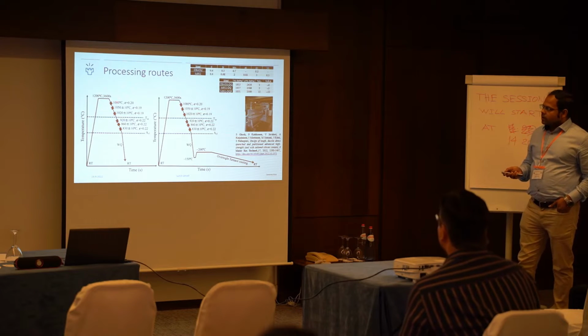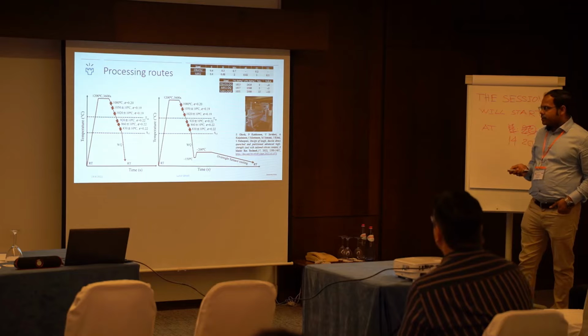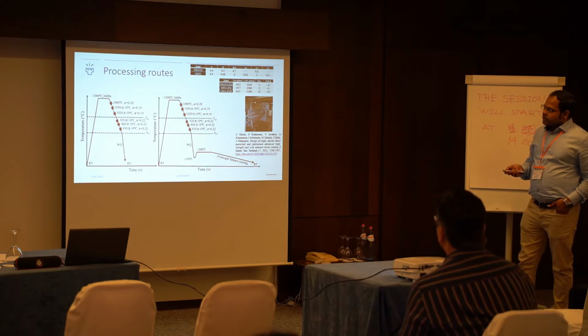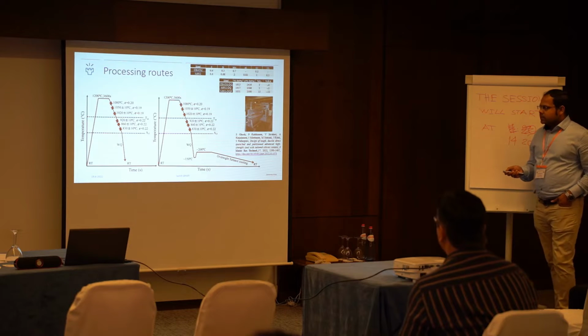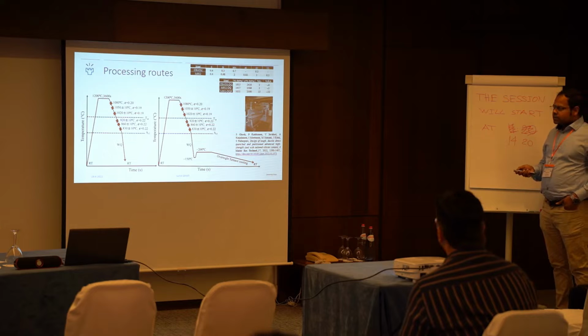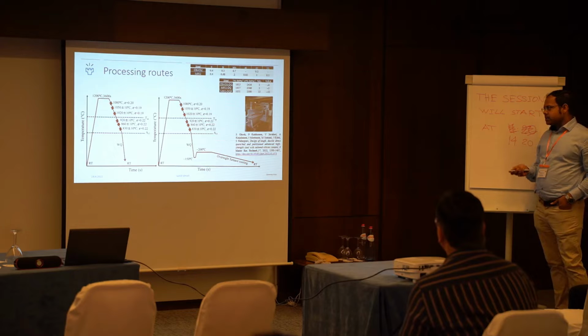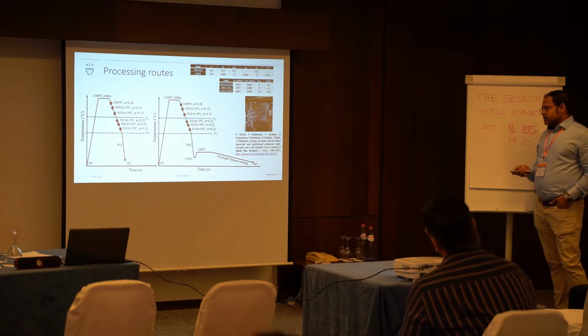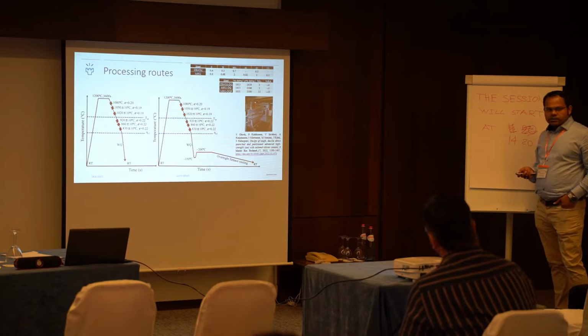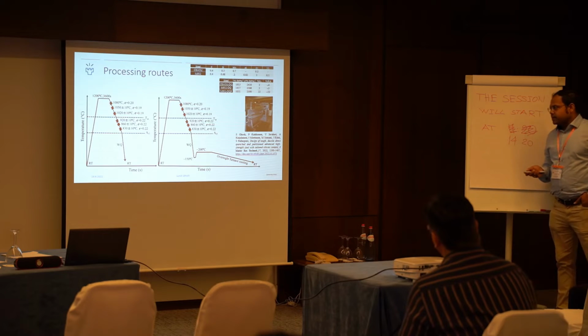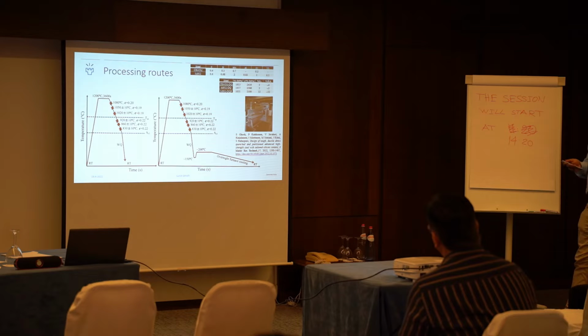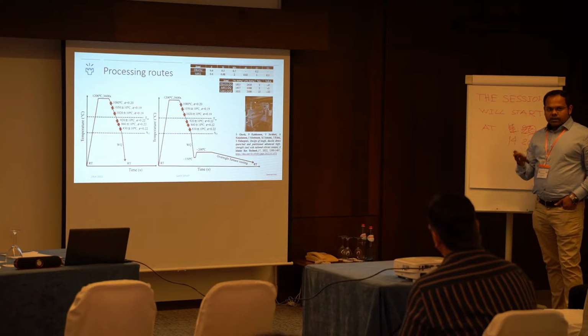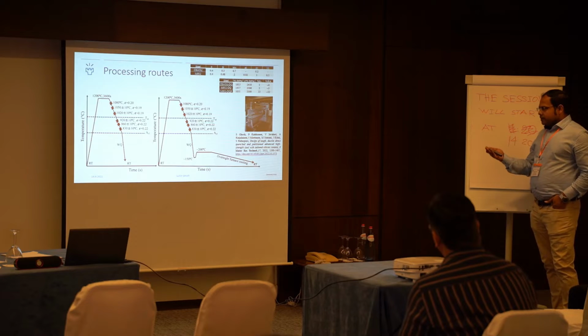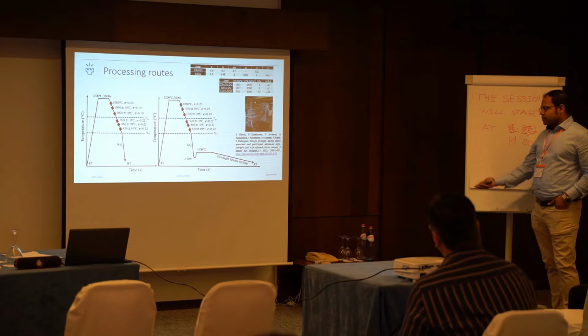So the first one is treated as a direct quench. Direct quench means we have conducted thermomechanical processing followed by quenching down to room temperature. In the second case, we have conducted thermomechanical processing and then quenched down in between the martensite start and finish temperature in order to attain a certain fraction of retained austenite and martensite combination. And then heat treated at a slightly higher temperature for a longer duration. The reason behind this heat treatment is to enable the enrichment of carbon from supersaturated martensite to austenite in order to make the retained austenite mechanically stable at room temperature.